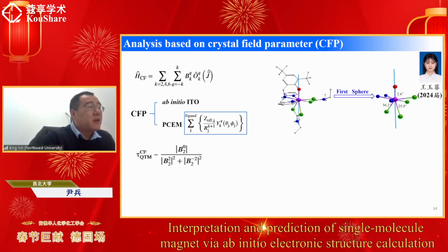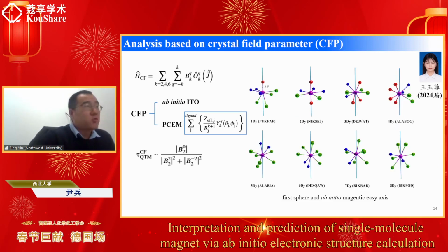And we found that for the 8 systems studied here, we could classify the atoms in the first coordination sphere into axial ones and equatorial ones according to their positions with respect to the magnetic z-axis. The ones close to the magnetic z-axis are classified as axial coordinating atoms, and the ones which lie approximately perpendicular to the magnetic z-axis are identified as equatorial coordinating atoms. So the red squares circle the axial ones, and the blue squares circle the equatorial ones.